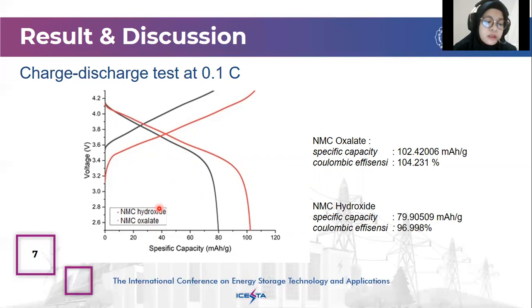When the curve shows a significant upward trend, the battery is charging. If the curve is significantly downward, the battery is discharging. The results indicate that NMC 811 oxalate has a higher battery capacity than NMC hydroxide. A good value of Coulombic efficiency is above 80%, and if it increases when charging quickly, it can prove that the battery system is stable. Therefore, from the result of the Coulombic efficiency, it can be said that both samples have good system stability.